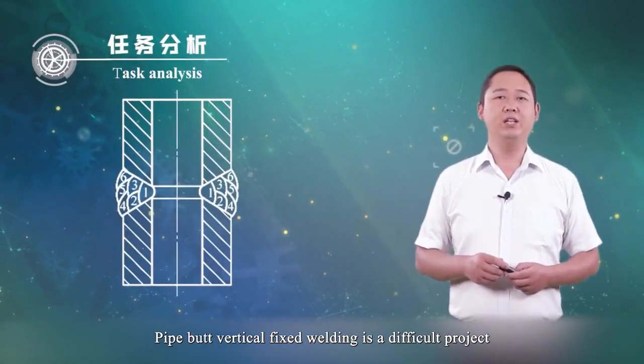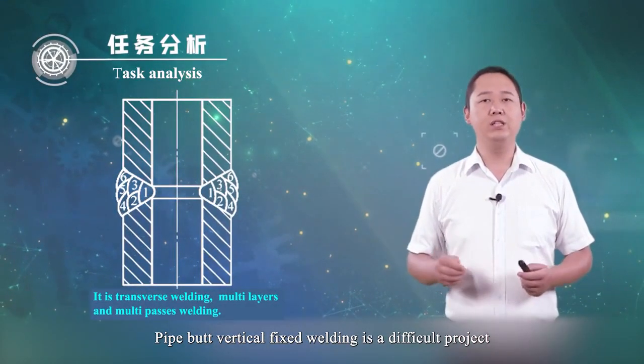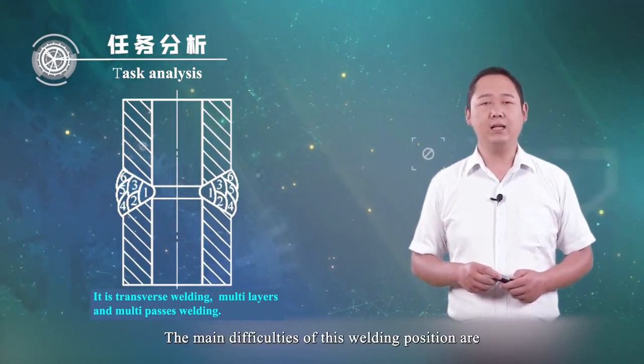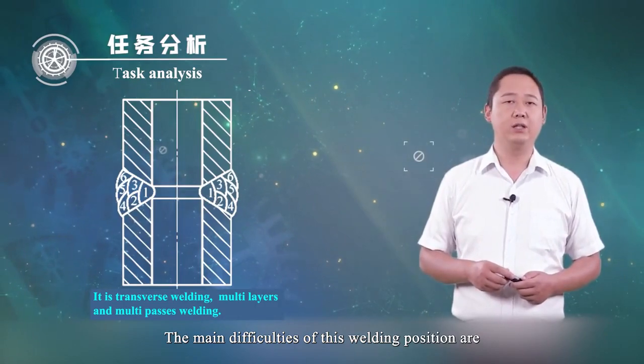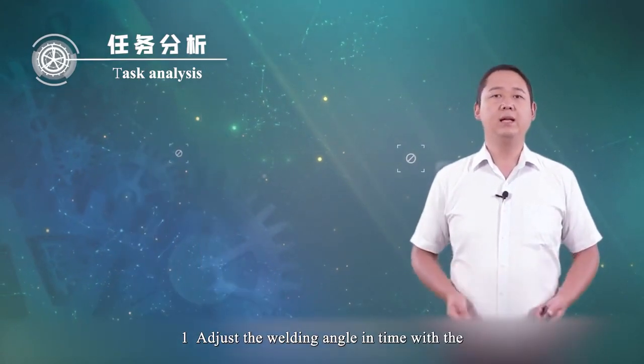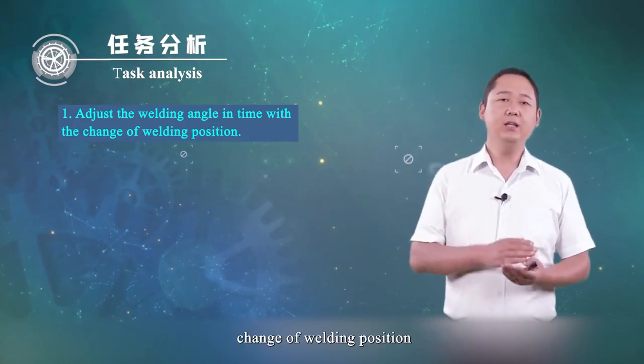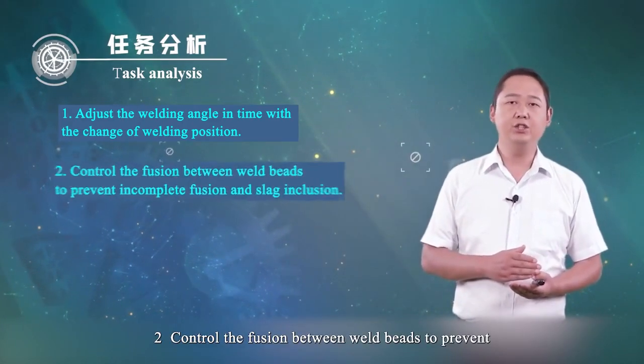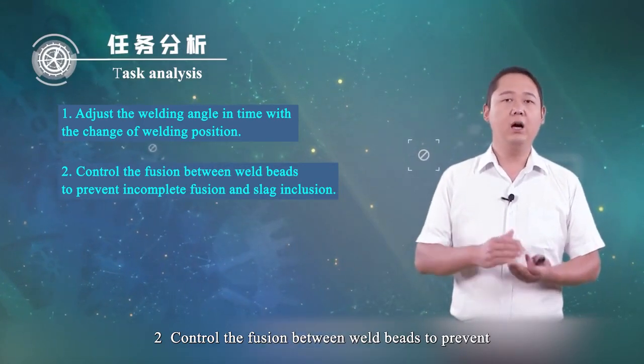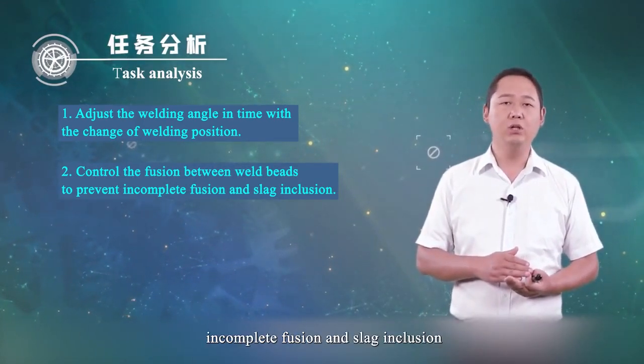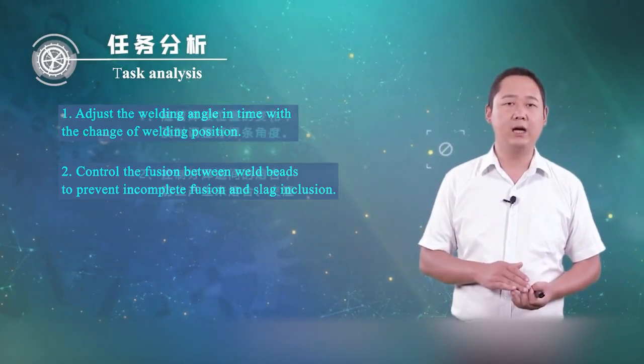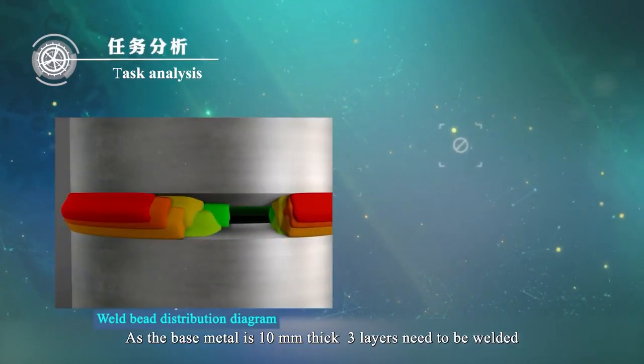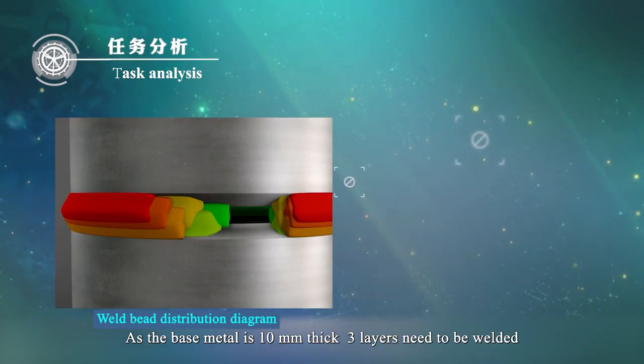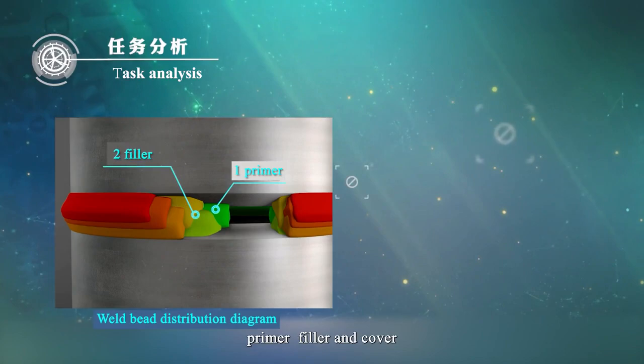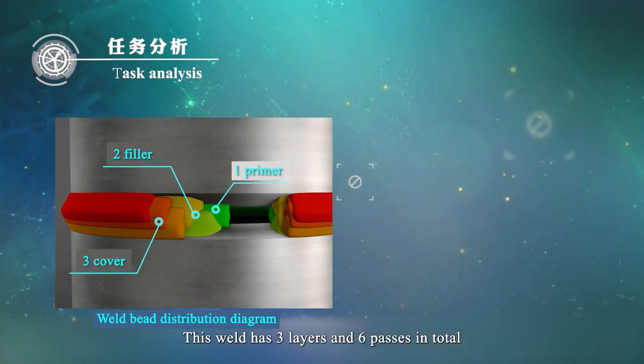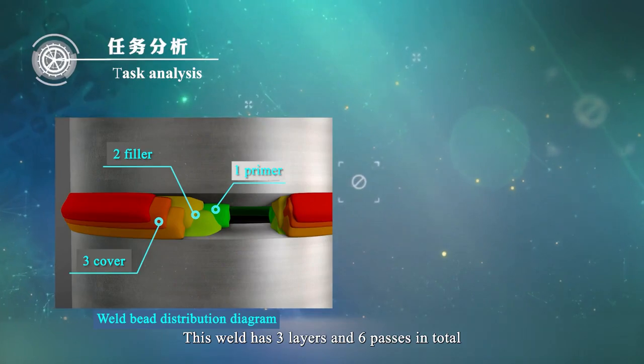Pipe butt vertical fixed welding is a difficult project in pipe butt welding. The main difficulties of this welding position are, first, adjusting the welding angle in time with the change of the welding position. Second, controlling the fusion between the weld beads to prevent incomplete fusion and slag inclusion. As the base metal is 10 mm thick, 3 layers need to be welded: primer, filler, and cover. This weld has 3 layers and 6 passes in total.